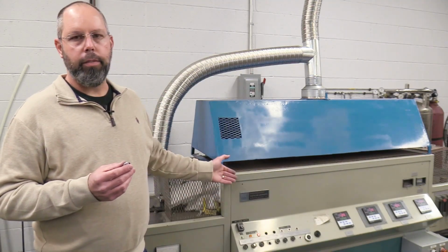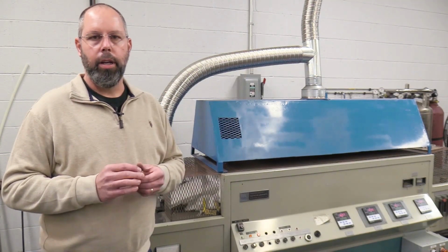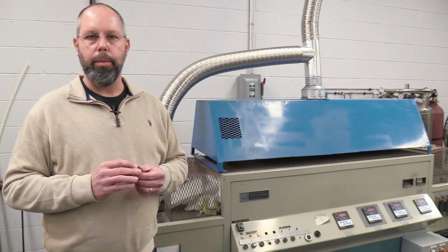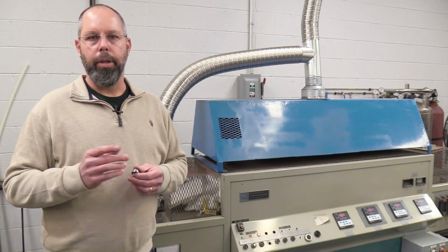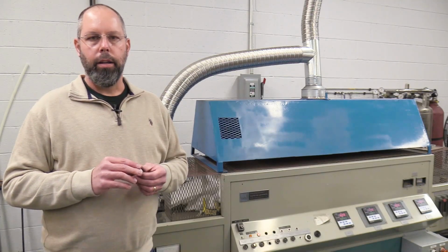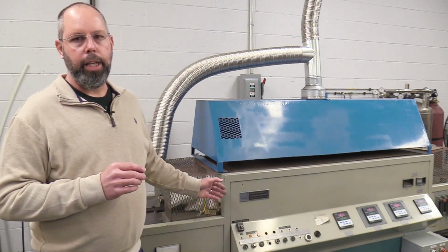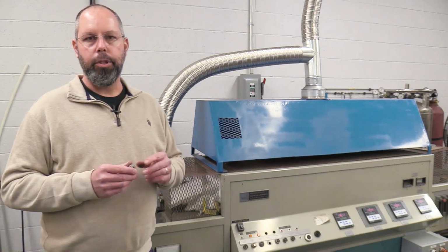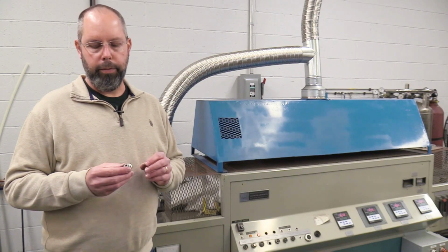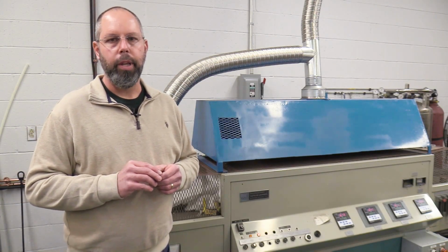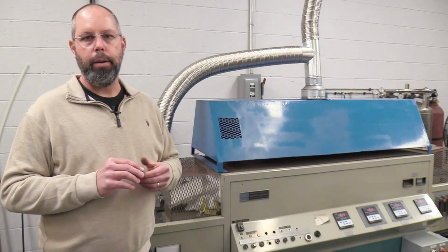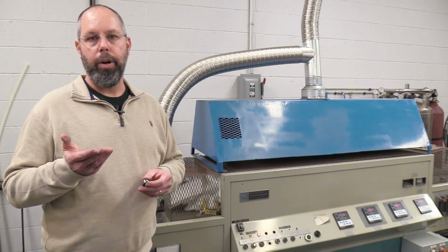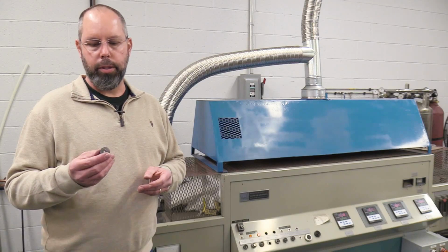Here's our lab version of an industrial sintering furnace. The problem with sintering is the particles need to be in contact with one another, but the lubricant acts as a barrier. So the first zone of the furnace heats the component up to a temperature that allows the lubricant to melt and be wicked from the part through capillary action. The subsequent zones of the furnace heat the component up to a higher temperature and allow the particles to be diffused together,